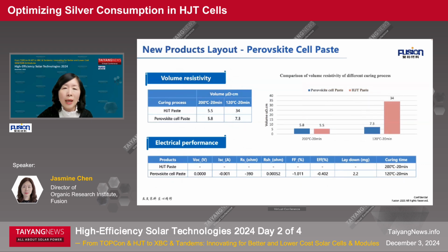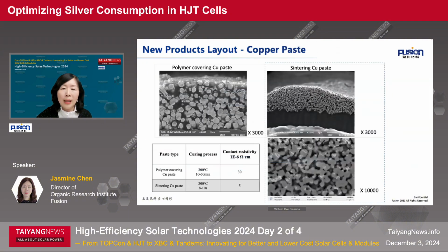This is another new product layout, a perovskite cell paste. We use a very low curing temperature, 120 for 20 minutes, and get an efficiency loss of less than 0.5 compared with regular pure silver paste. This is another new layout, a copper paste, using the new technology of sintering copper paste, which can significantly reduce the contact resistance.